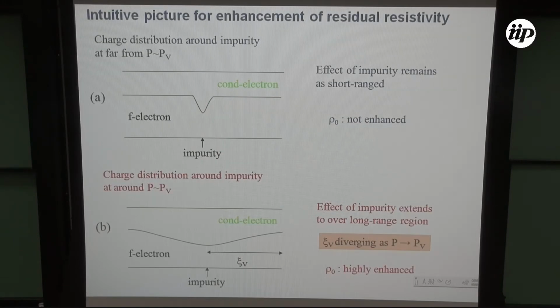So the intuitive picture of why the residual resistivity is enhanced so remarkably is like this. If far from the critical point, the effect of impurity is essentially short range, so that it gives no enhancement appearing in the rho zero. But near the charge transfer critical point, the change of the ratio of conduction and f electrons extends to infinity, so that this gives a highly enhanced residual resistivity.